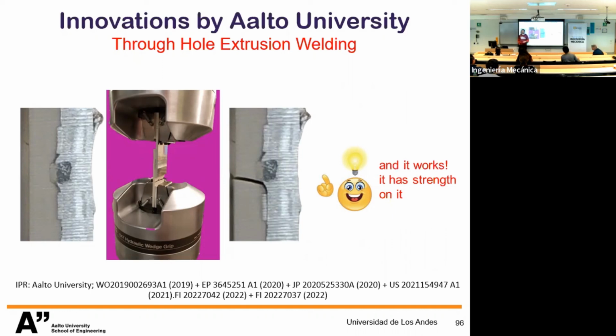How does it work? So what you see here is that we deform the aluminium, okay, and the polymer goes inside the aluminium, with a similar volume, and we have the clinching mechanical interlocking effect, okay. At high temperature, we have also some adhesive and some small diffusion.